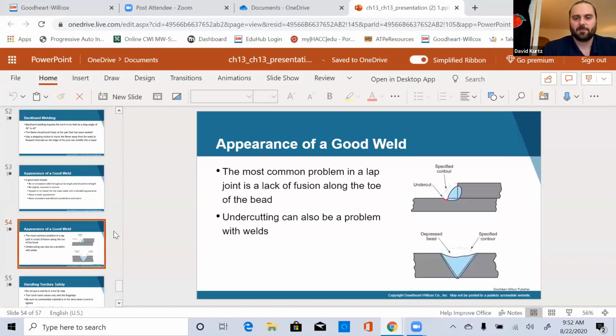Appearance of a good weld: the most common problem in a lap joint is the lack of fusion along the toe of the bead. So this would be an example of undercut. See how the base metal is cut into, and also it seems to me like obviously he didn't cap the top here. So you want to make sure that you cover both edges of the base metals. Here we just had not enough fill, so this would almost be like an underfill. You want to make sure that you at least have these edges burnt in and that the weld is flat or straight across from the base metals.